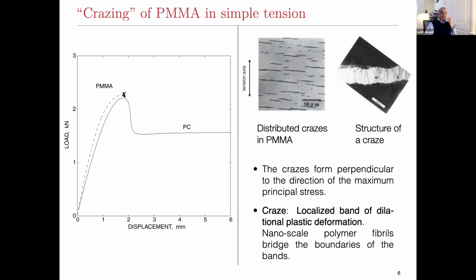If you look at the microstructure of the material, you'll see that it's filled with what look like crack-like features, but they really are crazes. Here's a higher resolution micrograph of one craze. What you see are these fibrils bridging the boundaries of the craze. A craze is also a band of localized deformation, but it's a dilational plastic deformation. There are holes interspersed with the fibrils, which bridge the faces of the craze, and eventually those fibrils will break, and you'll form a crack.